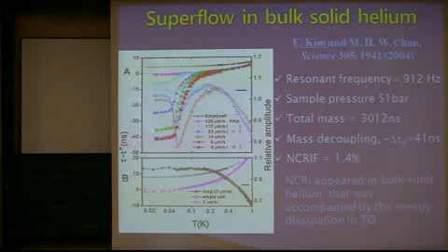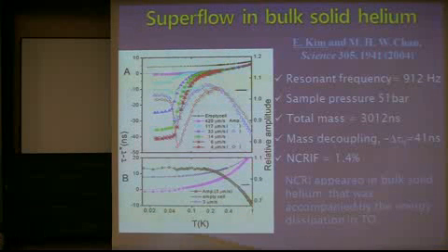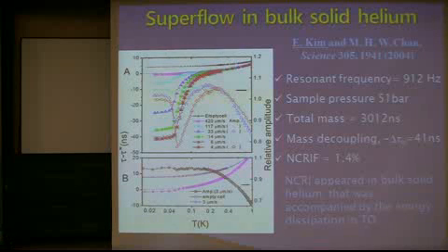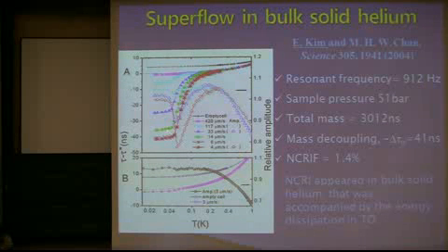Again, this is the resonant period as a function of temperature. If there is no change, it will just follow this line. However, there is a reduction in the resonant period, which can be interpreted as the appearance of non-classical rotational inertia. A similar thing was observed: when you increase the AC oscillation velocity, the effect is strongly suppressed. We also find energy dissipation with this kind of transition, and if you increase the AC oscillation velocity, it is strongly suppressed.